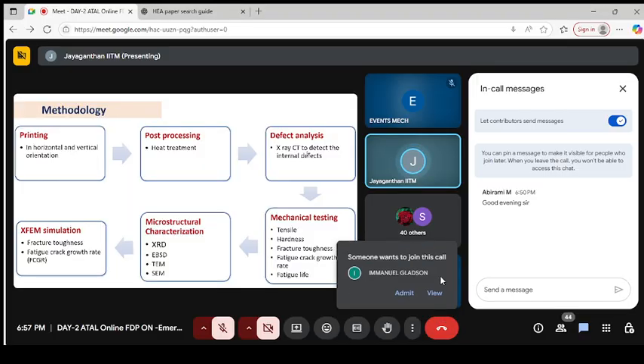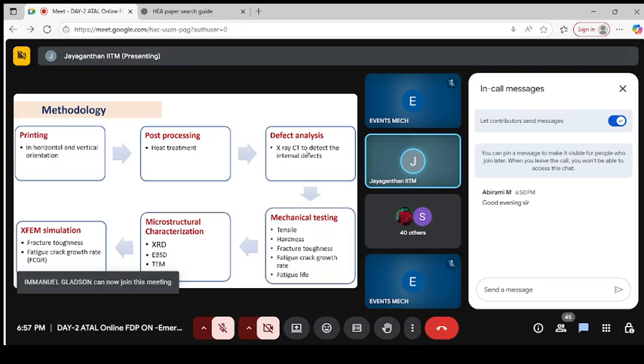After post processing, for the 3D printed sample we did the NDT analysis: an X-ray CT scan was done to see whether there are any internal defects in the 3D printed sample or not. And then, having done thorough characterization of the as-printed sample upon heat treatment, followed by analyzing the internal defects using X-ray CT scan. All the 3D printed samples, I mentioned, are 3D printed test coupons.